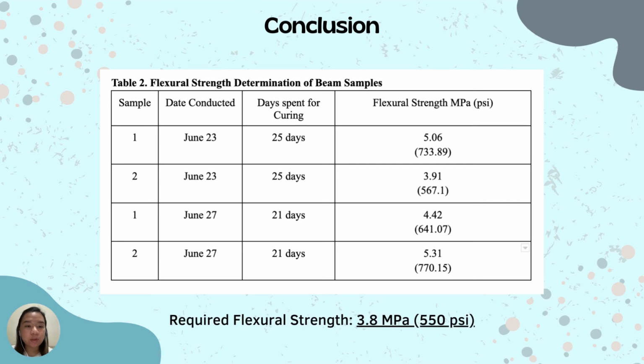Next is Table 2 for flexural strength determination of beam samples. The first batch, we have 2 samples, also conducted in June 23, spent 25 days for curing. We have 5.06 and 3.91. For the second batch, which was conducted on June 27, that spent 21 days for curing, we have 4.42 and 5.31 megapascals. So the required flexural strength is 3.8 megapascals or 550 psi. And again, as you can see, all the samples for the beam have passed the required flexural strength. With this, we can conclude that all the samples have reached their flexural and compressive strength before 28 days.